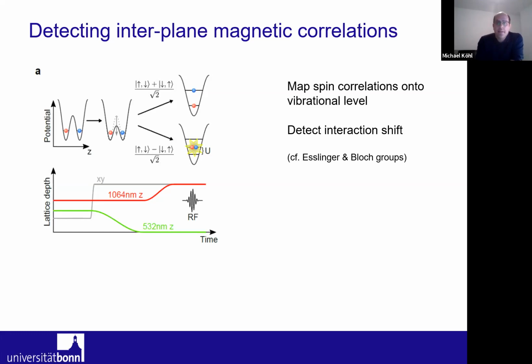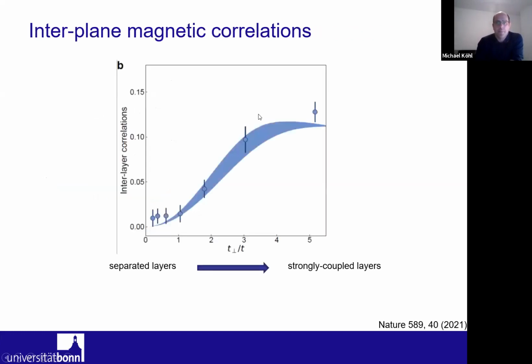And then we detect basically how many atoms we have either in the separate bands of the Z lattice, or how many are in the same band but shifted by the interaction energy. And so after appropriate normalization, we can now state what the interplane magnetic correlations are, and you basically see the exact opposite behavior.